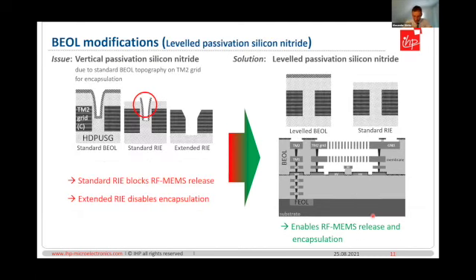The next issue is the vertical passivation nitride, which occurs due to the standard back end of line topography on TM2 grid for encapsulation. As I said, this actually belongs to the encapsulation, but from the fabrication point it belongs here. In cross section as a sketch, you see the TM2 grid, and this should mean a hole. Due to standard back end of line topography, we have vertical nitride. If we open the passivation nitride in order to release the MEMS, we have remaining vertical nitride, and this blocks the MEMS release. One option was to just etch more, but then in the end we have wider holes. So this was actually not possible to use for encapsulation.